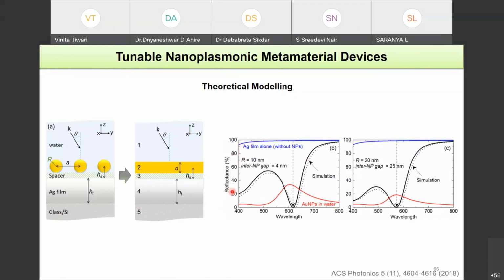So when you see this is the reflectance curve. So when there is only silver film and there is no nanoparticle anywhere, you'll see you get very strong reflection. You get almost 99% of reflection. But if you bring nanoparticles, which are gold nanoparticles of say 10 nanometer of radius and interparticle spacing of 4 nanometer, they're very densely packed, and you see the reflection curve gets a very strong dip. Sorry, the solid one is from this theory, and the dotted one is from COMSOL simulation. And you see that these two are very close to each other. We are able to predict this feature from our effective medium theory.